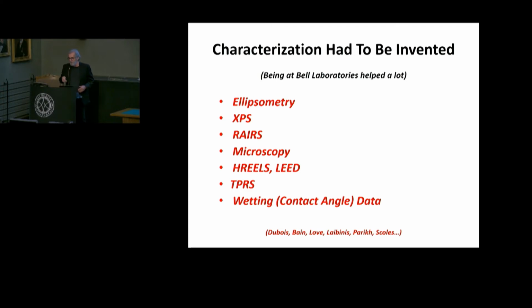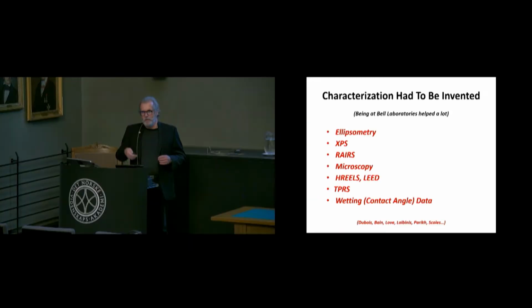Okay, so we do the first experiments, and that begets what I call my first experience with the "now what" moment. I did an experiment, and the properties of a gold film that I immersed in a particular adsorbate solution changed remarkably. And then, now what? Something happened, and the properties were such that you knew something really hydrophobic had formed at that interface. But beyond that gross characteristic, what was it?